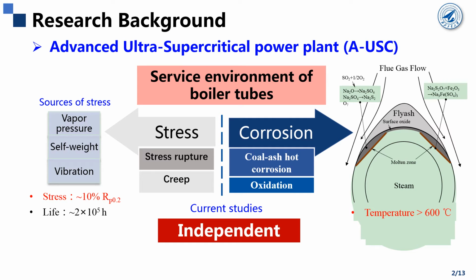In the advanced ultra supercritical power plant, the AUSC power plant, the service environment of boiler tubes is very complex. For example, the tubes are exposed to high temperature oxidation and the hot corrosion caused by the deposit of coal ash as well as the flowing flue gas. At the same time, the vapor pressure inside of the tubes, the self-weight, and the vibration also impose a low level of stress on the boiler tubes, especially for a very long term of exposure, as long as 10 to the power of 5 hours.